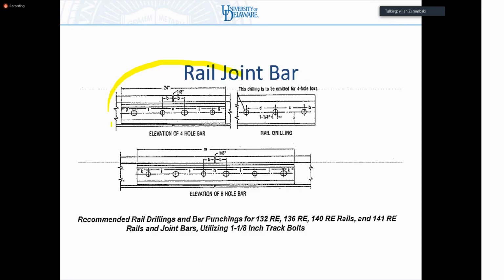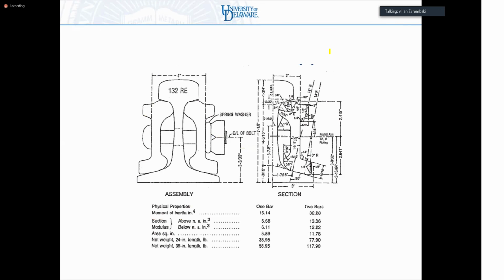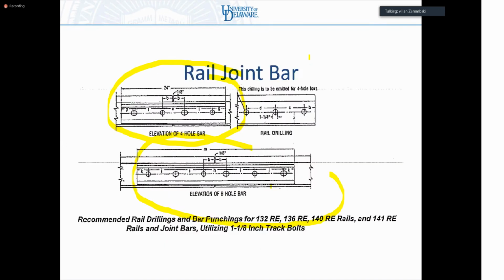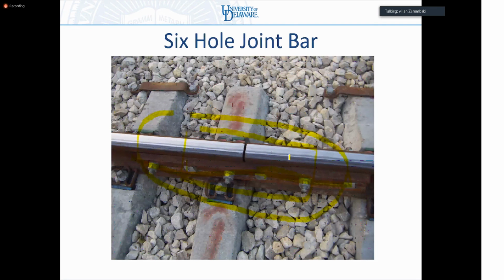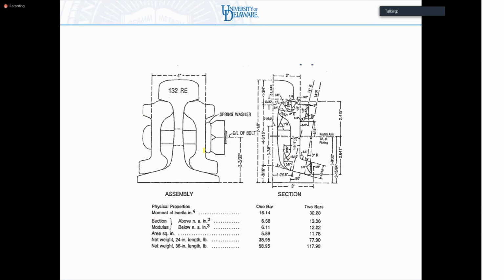Again, there's a 4-hole joint bar. There's a 6-hole joint bar. Again, these are for the heavier rail sections. These are for the small rail sections. Typical cross section of a joint bar. So what you're looking at now are these two sections over here. You can see it fits into the top fillet radius and bottom fillet radius of the rail. It does not go up into the area where the wheel flanges hit. As a matter of fact, if the rail wears to the point where the wheel flange hits the joint bar, that rail has to be replaced. You cannot have the wheel flange hitting a joint bar. That's a recipe for disaster.